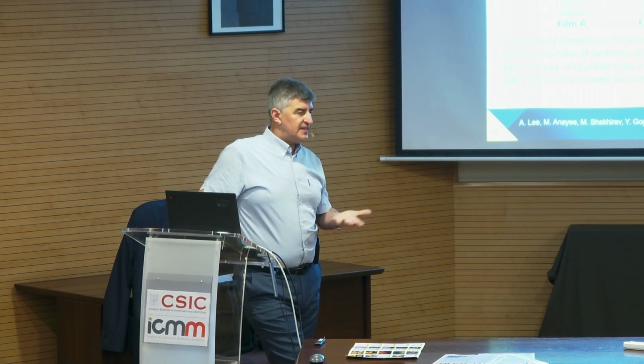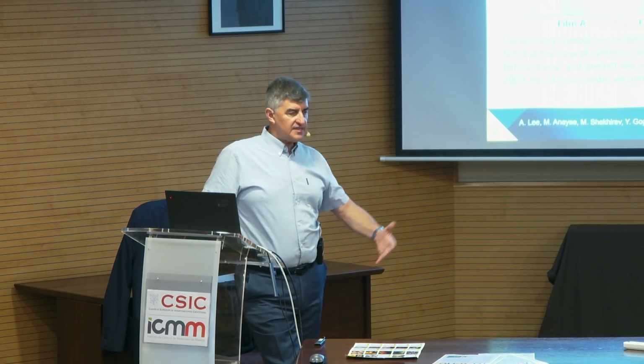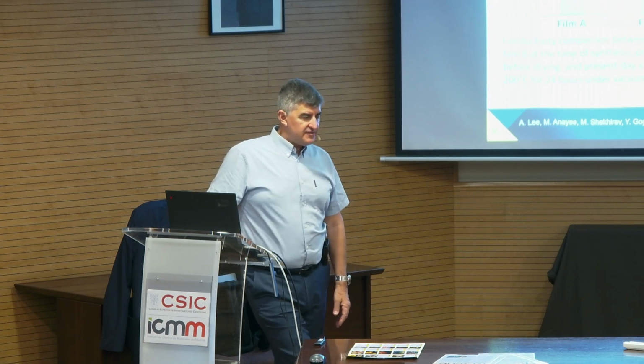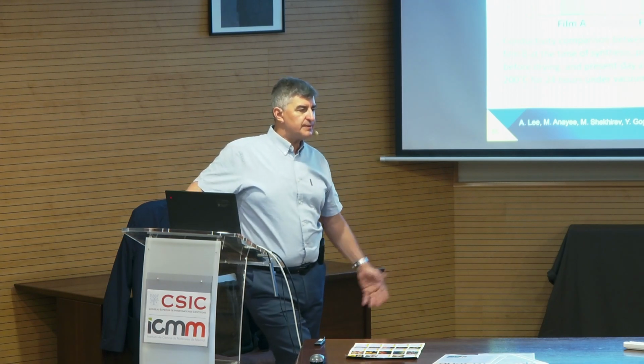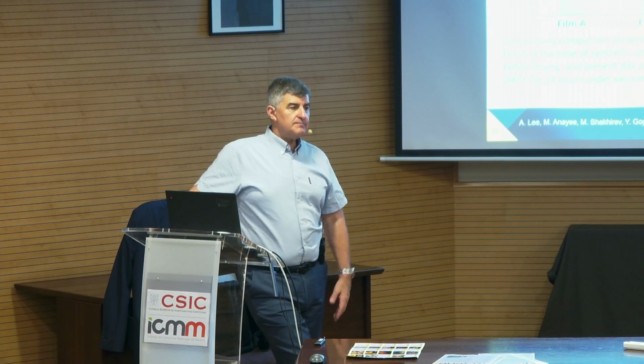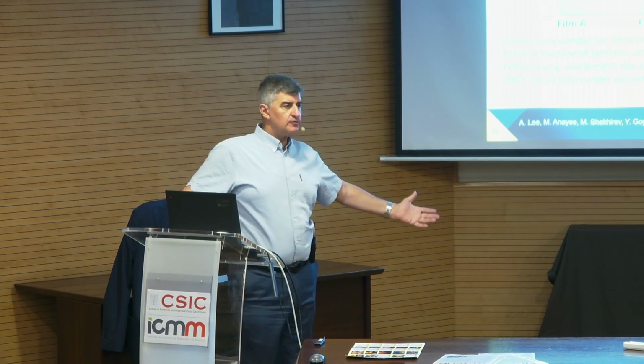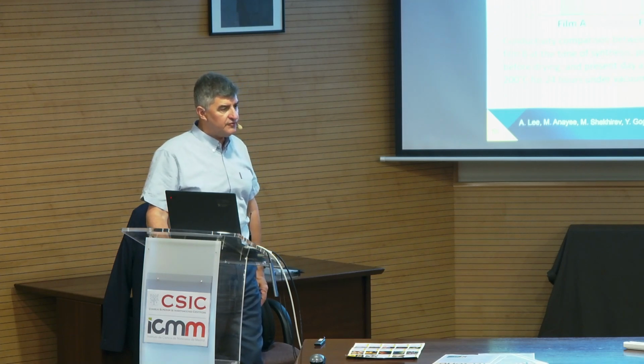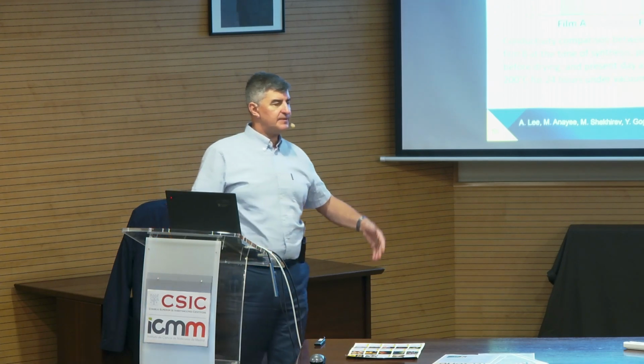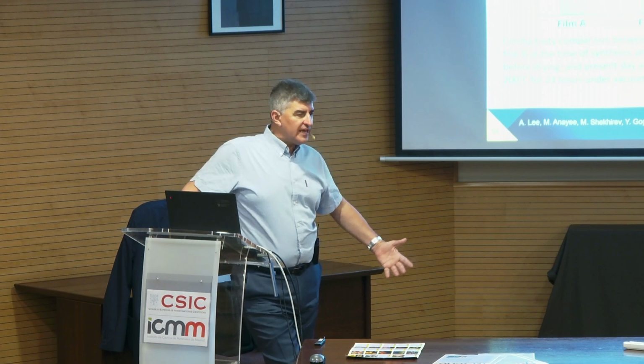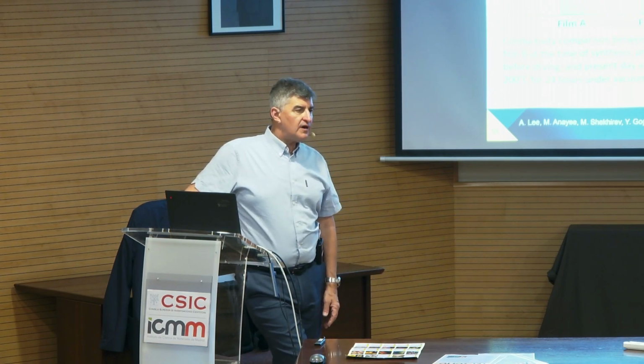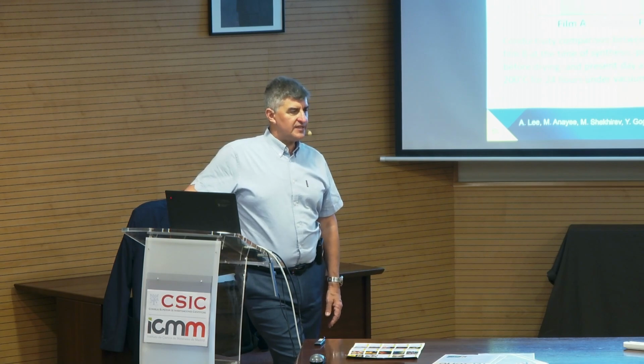So fundamentally, I don't think there should be a limit for this. They can potentially be grown by CVD on the surface. They can also be produced in larger flakes, maybe also assembled from organic molecules, like it has been done for graphene on the surface, taking for example metal organic compounds. But so far, we are talking about flakes from microns to lower tens of microns.